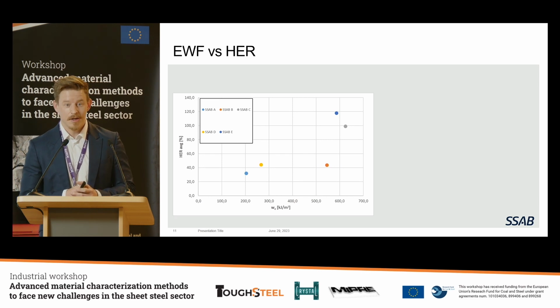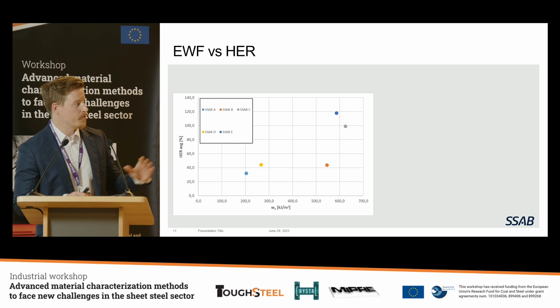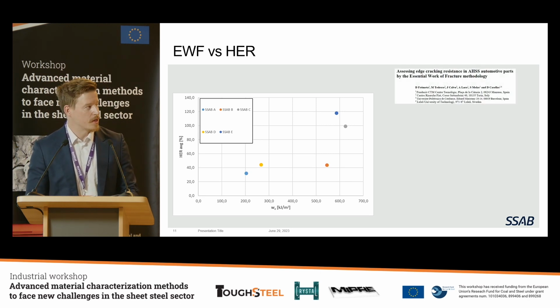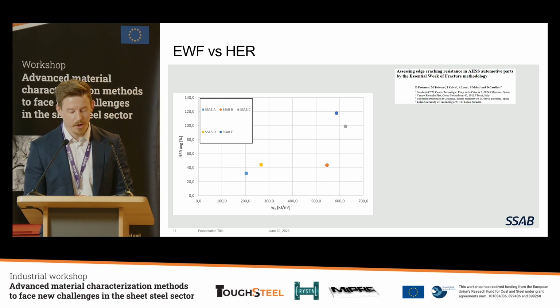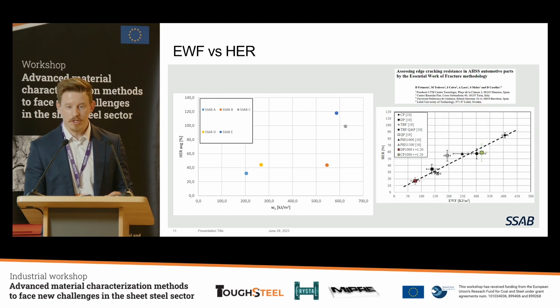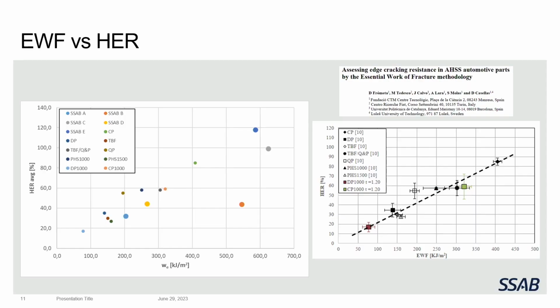Here you can see the results from these 5 materials. And before going into this, I would like to bring Mr. Frómeta's previous published work, including much more results for different kinds of materials. And you have found a really nice correlation for the materials, essential work of fracture and hole expansion ratio. Now I took all these results from a previous publication, and you can see now the small dots in our figure on the left. And actually what we can see is that those old results and the new results are aligning really nicely. We can actually see the correlation there.